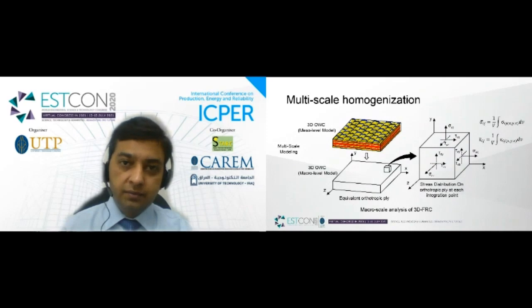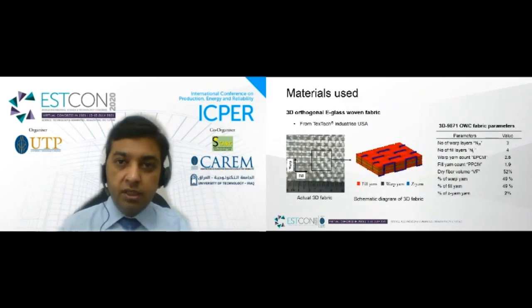So now the 3D fabric used in this study is 3D orthogonal e-glass woven fabric, which is obtained from TexTech Industries, USA. The fabric consists of 3 layers of fibers along warp or X direction and 4 layers of fibers along fill or Y direction. The dry fiber volume fraction of this fabric is around 52% and it has 49% yarns along warp and fill direction.